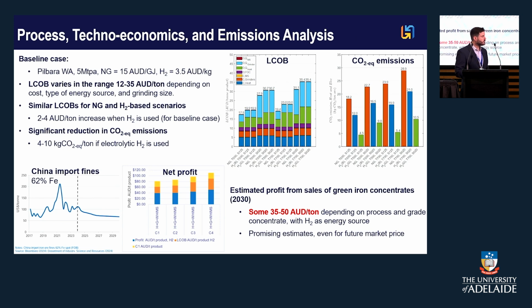The beauty of the thermal treatment here is that it can be provided by either natural gas or biogas, and also hydrogen and other sources. Of course, from our current estimate, the levelized cost of beneficiation really depends on which energy source, the cost of the energy source, but also how fine you grind. You see, it's quite significant, the grinding energy to the total LCOB. But on average, we were able to show that the LCOB can be between $12 to $30 per ton. That, when compared to the current and also future market price for Fe to China, still leaves quite a healthy profit for our partners.